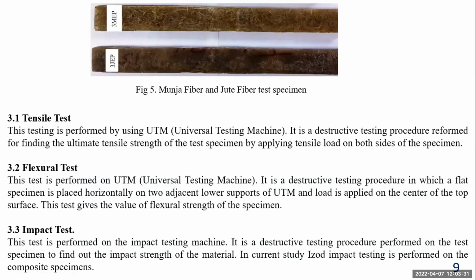The tensile test is carried out on the universal testing machine, in which the load is applied on both sides of the test specimen. The flexural test is also carried out on the universal testing machine. It is a destructive testing procedure in which a flat specimen is placed horizontally on 2 adjacent lower supports of the UTM, and the load is applied on the center of the top surface. This test gives the value of flexural strength of the specimen.